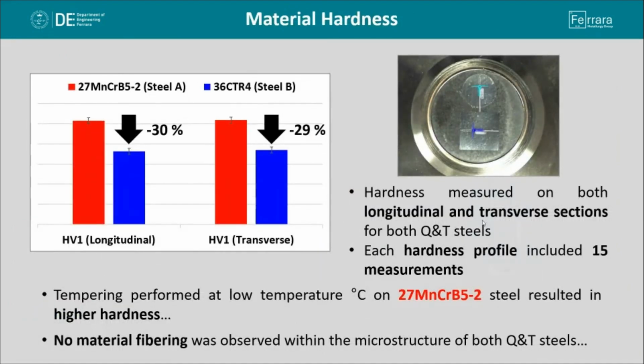Now, moving on to hardness test data, even hardness turned out to be greater for steel A with respect to steel B because of its sorbitic microstructure related to tempering performed at higher temperature. Hardness was measured by means of hardness profiles carried out on transverse and also longitudinal sections of metallographic samples extracted